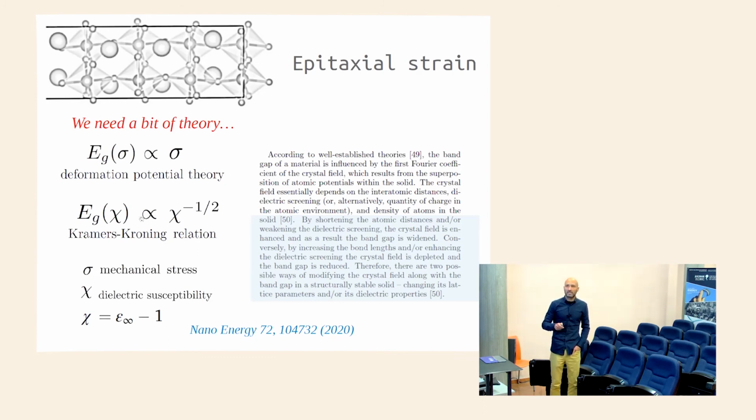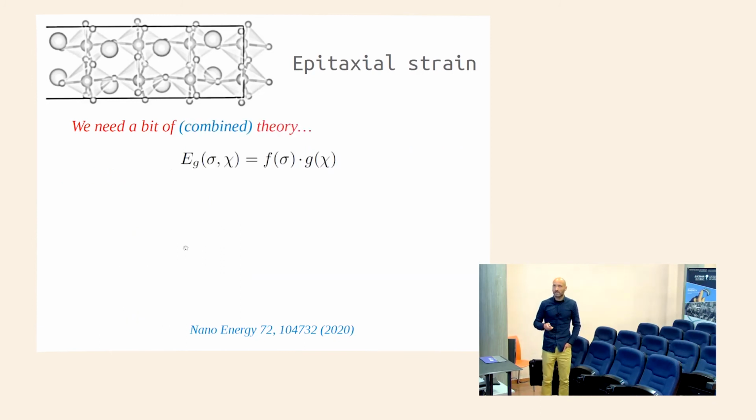So I would say that so far, people in the field had just taken into account this contribution, but this other part, which has to do with the many-electron, the dielectric screenings, which is something that acts more in the medium and long range, had been pretty much overlooked, right? So what we did was to consider a very simple analytical model, in which we assume that the energy band gap could be changed by two different sources: by changing the stress, or if you want, the distances between the atoms, and by changing the electric properties of the material, right?